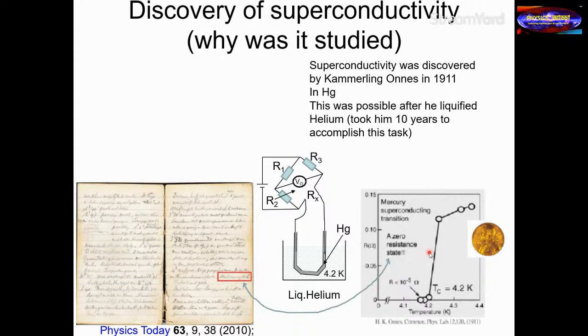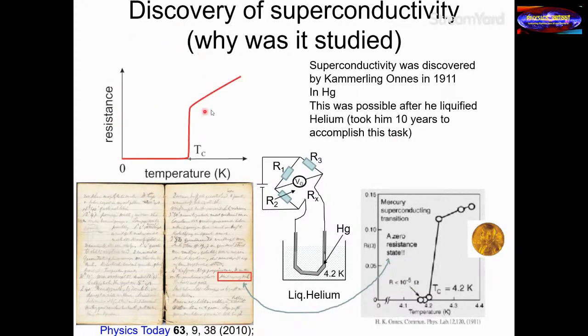it is a material, if it is cooled below a certain temperature called the critical transition temperature, then the resistance of the material tends towards zero. Okay. So if you take a material and you measure its resistance, then below its critical transition temperature, the resistance of the material becomes immeasurably small. It becomes very low. So the Wheatstone bridge method, which Kamerlingh Onnes was using in 1911, this was the discovery which happened in 1911. This is his notebook in which it is mentioned that resistance actually becomes zero, where the resistance goes below whatever the sensitivity of his instrument was, 10^-5 ohms. So it is below 10^-5 ohms.